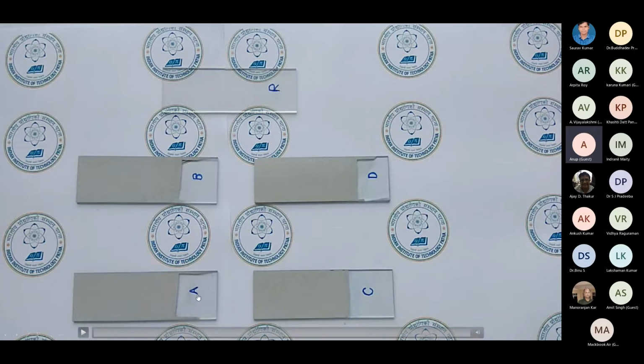Now image A which you are able to see here is the digital image of the aluminum coating, which we claim to be super hydrophobic, where the water contact angle is very high, more than 150. B is hydrophobic, meaning greater than 90 degrees but less than 150 degrees. C is less than 10 degrees, super hydrophilic, and D is hydrophilic, that is greater than 10 degrees and less than 90 degrees, and R is the completely uncoated substrate.